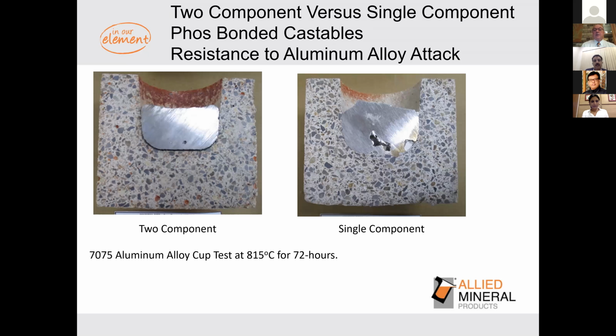To meet that challenge, we did not want to lose any of the benefits of the phosphoric system of the 2-component. So we started running tests. This is just an aluminum cup test without the salt flux and with 7075 alloy. And you can see that we run the test at 815 degrees C because, again, in my experience, looking at oxidation graphs of aluminum at 815 degrees C, the oxidation is astronomical. I mean, it goes up from liquid to an oxide. The slope of the curve is vertical.